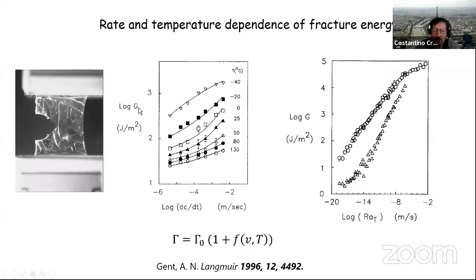I mean, indeed, fracture energy, this is data from Alan Gent from '96. If you look at the data at different temperatures, you can build a master curve. You can actually use the shift factors that worked for linear rheology to superpose this data. So you could really say, well, linear rheology is important to explain this dependence of G as a function of RT. And so in principle, you could build a model with that.